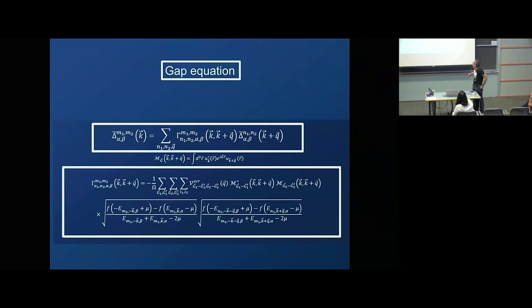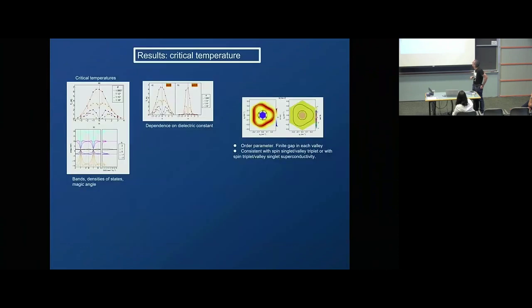And this is a kind of formal thing, how we solve the problem. We first tried TBG, twisted bilayer graphene, and we found superconductivity of the F-type, similar to the superconductivity I mentioned before for this toy model invented by Kreppel and Fu, with relatively large critical temperatures in the order of 1 to 5 Kelvin.